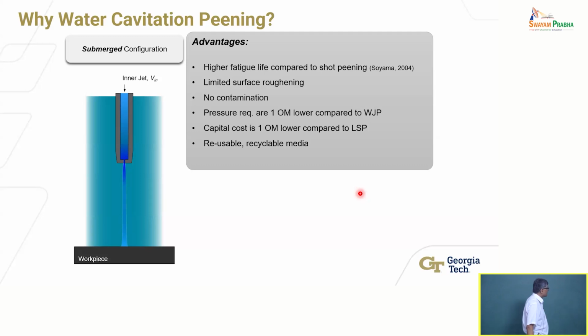These are the reasons. There are some other reasons as well. Higher fatigue life can be generated compared to shot peening. People have shown that. Limited surface roughening, that's important. Shot peening, where you have mechanical shots impacting the surface, also tends to roughen the surface. Roughness is bad for fatigue life. So there's some optimization required there. You can tolerate some roughening as long as you are inducing sufficient compressive residual stresses. But water cavitation peening will produce less roughening and induce compressive residual stresses to a similar extent or even more. That's the other reason why you want to do it. Also, the media is reusable and recyclable; water can be recycled, etc.